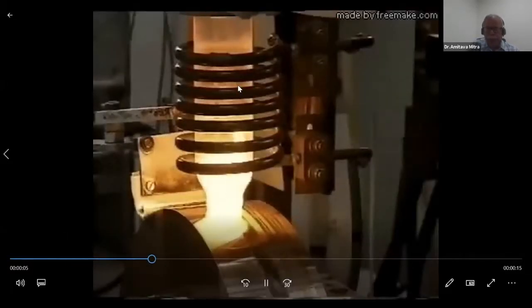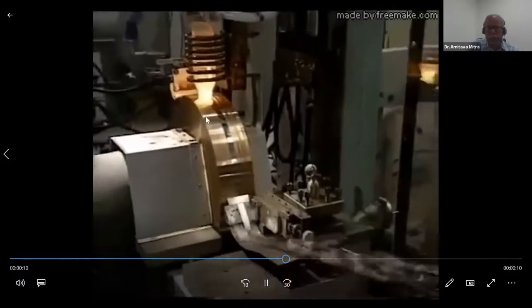This is that liquid metal, this is the crucible, and this is my induction coil, and this is my copper wheel. The copper wheel extracts the heat so that this goes into the supercooled region, and by that way we can cool this material at almost 10 to the power 6 Kelvin per second. Because we are taking the heat away, this material thickness has to be of the order of 20 to 30 micron. If it is more than that, it will be very difficult to get this amorphous structure, because in that case the extraction of heat will not be that good.